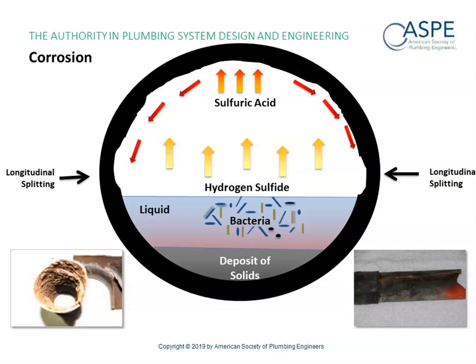We then get an anaerobic process with bacteria eating and decomposing these solids, which off-gases hydrogen sulfide. I know most of us have done some field work, and you know what a dry P-trap smells like, which is why there are trap primers and other interesting things on the market to keep that 2-inch standing water, to keep this hydrogen sulfide from entering your building. Hydrogen sulfide doesn't only stink, it is a lethal gas. If you are in a confined area with hydrogen sulfide, it can literally paralyze your lungs. So imagine you have a breached piping system and you're working in a confined area for an extended period of time with this condition, it can actually be fatal.